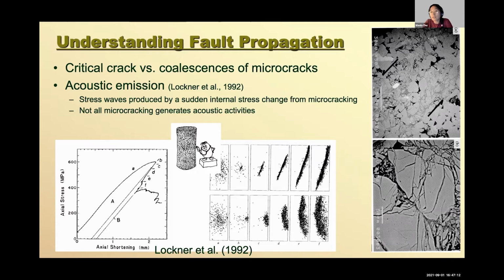Obviously, with these snapshots, you don't know how these micro cracks developed. That's why in the early 90s, pioneered by Dave Lockner in the USGS lab, they used acoustic emission. During the deformation, while the crack is developing, you can listen to it, because micro cracking is essentially little micro earthquakes while the crack is propagating.